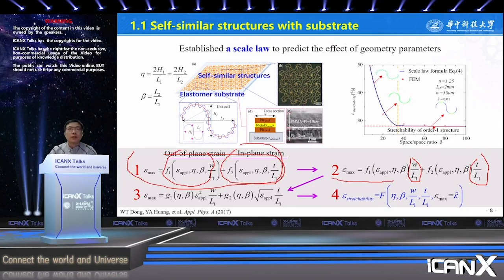Thirdly, in the same way, we can get that the first part of the maximum stretch is linearly proportional to the square of the external strain, and the second part is linearly proportional to the square root of the externally applied strain. So we can get the scale law like the third equation. Finally, we let the maximum equal the yield strength. One can get the stretchability like the fourth equation. So we can predict the stretchability.